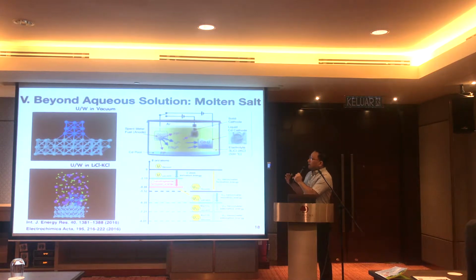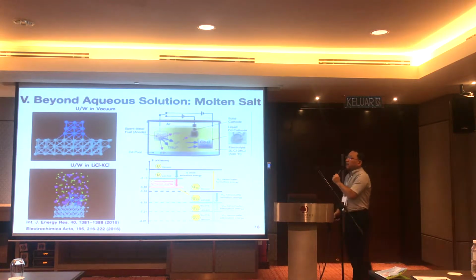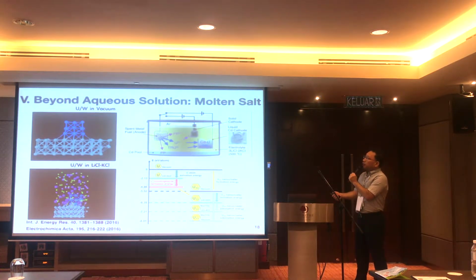But anyway, after 1 year or 3 years or 5 years, depending on the nuclear reactor type, once you burn out the uranium in nuclear power plants, there is still a lot of uranium that has not reacted. So we want to recycle nuclear fuel from that spent nuclear fuel. Once you take out spent nuclear fuel and dissolve it in molten salt, you want to recycle exactly the uranium, not other materials. There is a huge amount of uranium and a huge amount of rare earth materials.